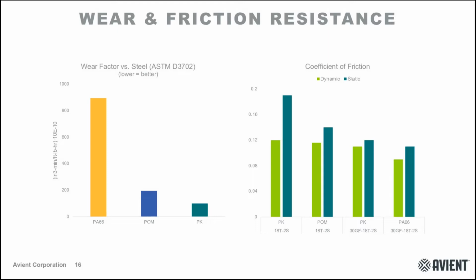Additionally, additives like Teflon and silicone can be added to polyketone to reduce the coefficient of friction, similar to what you would expect of other wear-resistant low-friction thermoplastics like acetal and nylons. So this makes polyketone attractive for applications in which wear resistance or low friction are crucial. These could be things like bearings, gears, slides, and conveyor belts. And that's shown again in the graph on the right.